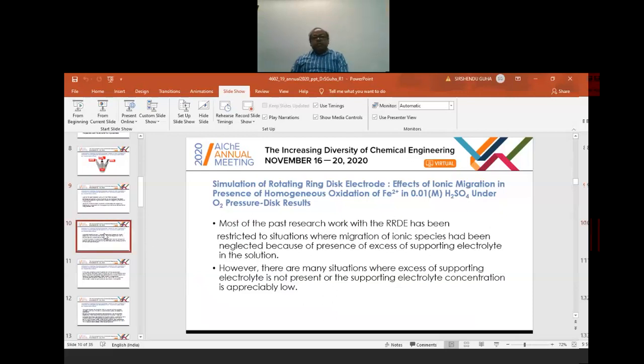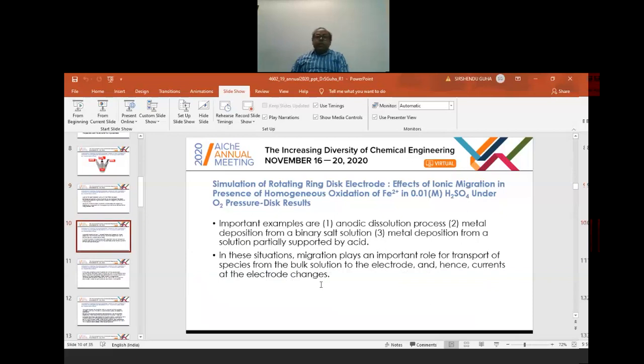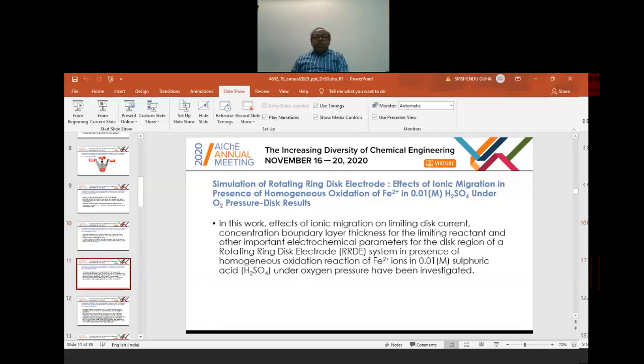But there are many situations where the supporting electrolyte cannot be used. Important examples are the anodic dissolution process, metal deposition from a binary salt solution, and metal deposition from a solution partially supported by acid. In these situations, migration plays an important role because we cannot use supporting electrolyte or the supporting electrolyte concentration is very low. And due to presence of this migration mode of transport, the currents at the electrodes are affected. Now, this is what I have already spoken.